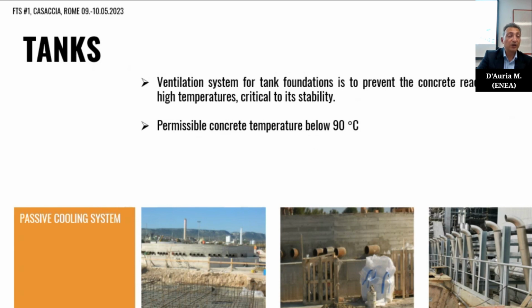So now we consider some details regarding tanks, and that is the thermal energy storage. The purpose of the ventilation system for the tank foundation is to prevent the concrete from reaching a temperature critical to its stability. Using normal concrete, this temperature must be kept below 90 degrees. The pipes must therefore be able to remove the heat flux from the bottom of the tanks at the interface with the insulation and the concrete.